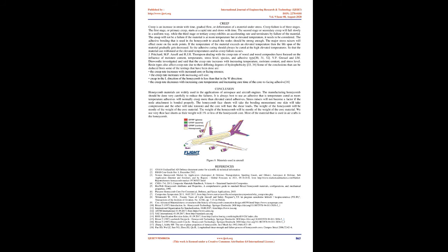The fatigue life of a component will also be adversely affected by damage, though the magnitude of this reduction in fatigue life is often more difficult to establish. 27, 28. The fatigue of damaged structures with initial defects may be determined by the extensive testing of specimens with various defects at different load levels. 29. The honeycomb factors that influence the fatigue limit of the core are recorded underneath along with some broad remarks.